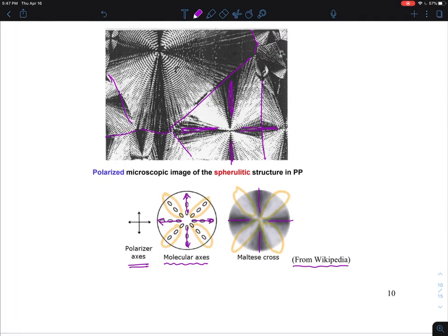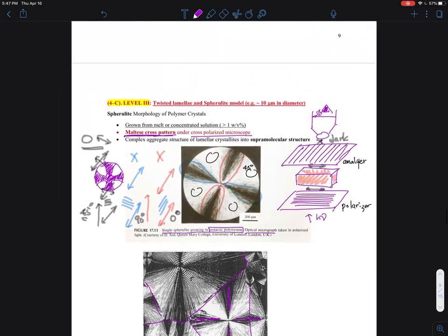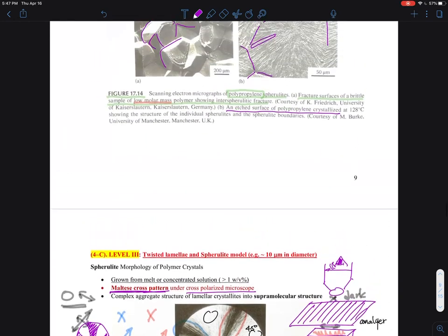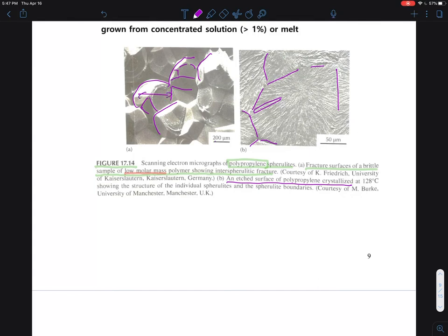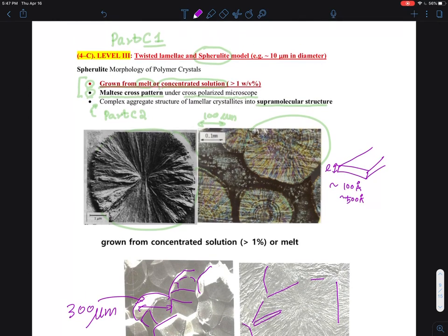So the big message here is the size — this is about 200–300 microns. The lamellar crystals start to pack together, grow, and eventually bump into each other in three dimensions, forming a faceted spherulite when grown from the homogeneous melt or rubbery state. This concludes section part C1 about the spherulite — grown from the melt or concentrated solution — and the Maltese cross pattern, which is a distinct piece of evidence showing you have a polymer crystal in spherulite form using the cross-polarized microscope.